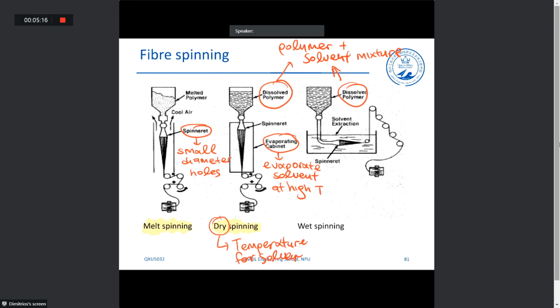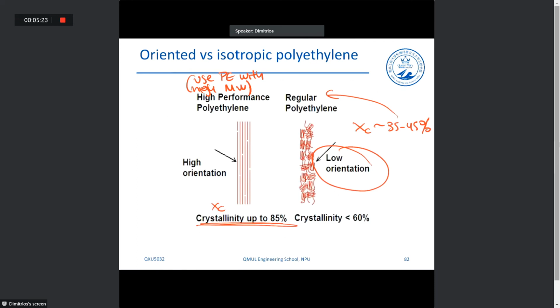Yeah, these are some examples on essentially the performance and the characteristics of oriented materials, such as polyethylene, which is a very common material we use for the fabrication of high-performing fibers. Usually, as we said, it's ultra-high molecular weight polyethylene that performs the best, and that is because the chains in ultra-high molecular weight polyethylene are very large in number, but also large, okay? And because they're large in size, if we manage to orient very long chains, we achieve even higher degrees of crystallinity.